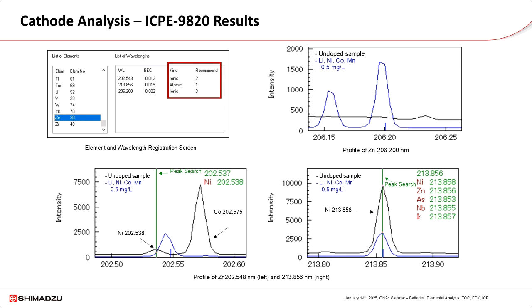In addition, the all wavelength data acquisition function allows wavelengths to be added after the fact. As shown in the lower figures, the peaks of nickel and cobalt overlap with zinc at 202.548 nanometer, and the peak of nickel overlaps with zinc at 213.856 nanometer. These two wavelengths are not suitable to be used to quantify zinc in these cathode materials.